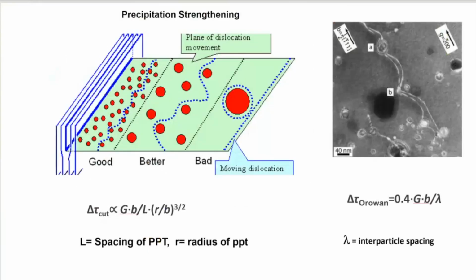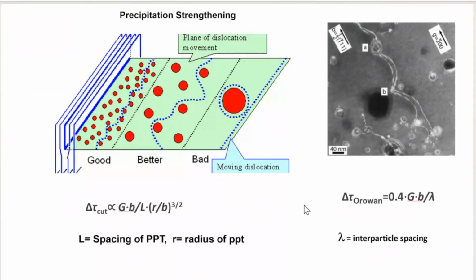But the most common strengthening is precipitation strengthening. And this strengthening depends on the size. If it is a small size, then it is quite effective to stop dislocations. And the equation that you see in the slide gives you the shear stress required to cut these particles. And if particles become very big, of course, you have Orowan looping, and the dislocation can go around it and move together.